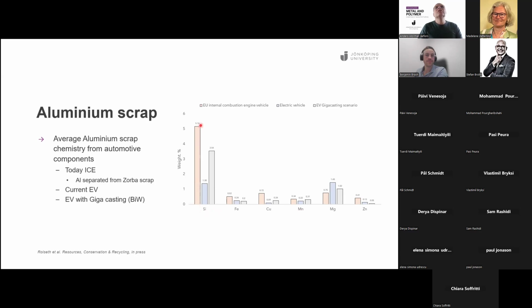And if you think about this, you have 5% in the scrap that comes back as Zorba scrap, and then you try to make a casting alloy of that. So you need to go from 5% silicon to 7 or 8 or 9 or 10 or 11 or 12% silicon. So that is quite a hefty addition that you need to make. Now,